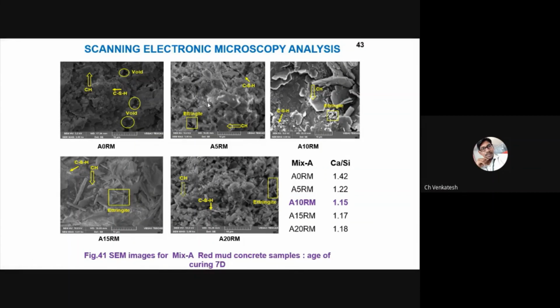So here you can clearly observe this is the no red mud concrete. These are the red mud replaced concrete. In case of no red mud concrete, you can clearly observe that the voids are present there. But in case of red mud concrete, fewer voids and cracks were present. And moreover, you can clearly observe the ettringite formation and the polygon shapes, which we call calcium hydroxide, and also the flower-like structure CSH. We can clearly observe these in the red mud based concrete.